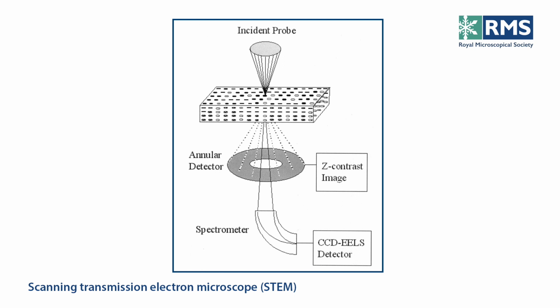And then you observe the scattering in an annular detector, the so-called Z contrast image, in which the different beams are in fact scattering incoherently. And you can also then send the beam into an EELS detector, an electron energy loss detector, so you can do a scan of the electron energy loss in the material. Show you an example or two.